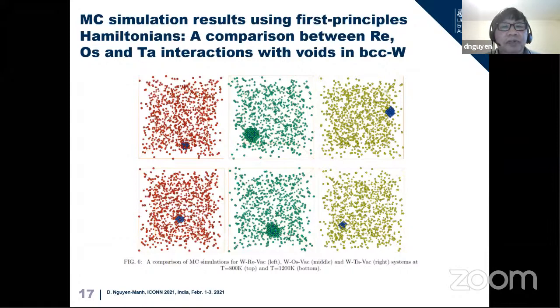So the first Monte Carlo simulation is to compare rhenium, osmium, and tantalum interaction with the void in BCC tungsten. The most important thing here is that I show two temperatures. Here is a Monte Carlo simulation. The red atom here is rhenium, green here is osmium, and yellow here is tantalum.